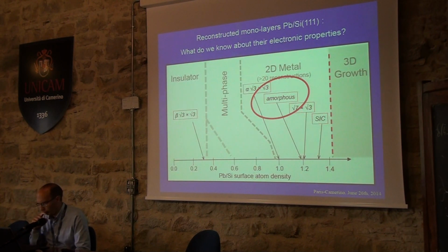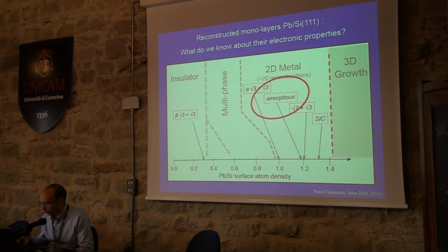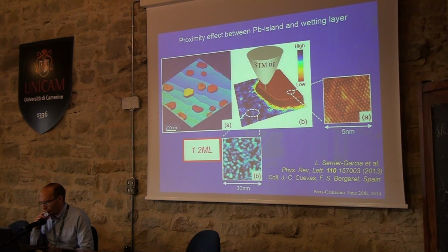So now we turn to the case of single atomic layers of lead. The first case is the amorphous wetting layer. When you deposit lead atoms on your surface, the islands grow, and the wetting layer, which is in between them, is not crystallized. It is amorphous, as shown by the topographic image on the bottom, small square image B in this picture. The islands are crystalline, as shown by the right inset of a scanning tunneling microscopy image showing an atomically resolved lead surface on the island top.